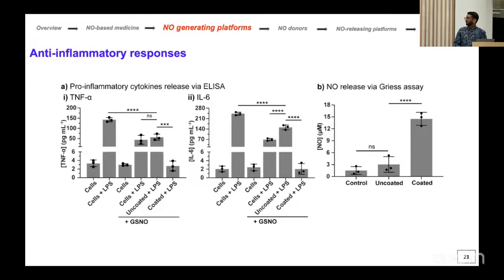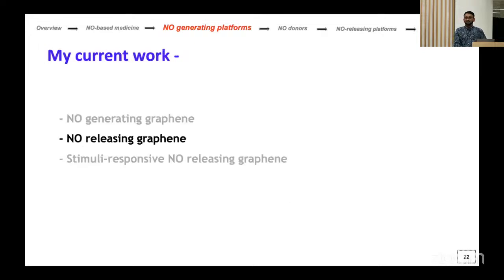And then, okay, so we see that basically there is an effect and there is a reduction in these markers. So why? As we are claiming that this is because of nitric oxide, we measured nitric oxide using the Griess assay to show that the coated device has a higher generation of nitric oxide. Another study on nitric oxide releasing graphene. These next two studies are about injectable particles which we are using for myocardial infarction and ischemia reperfusion injury.